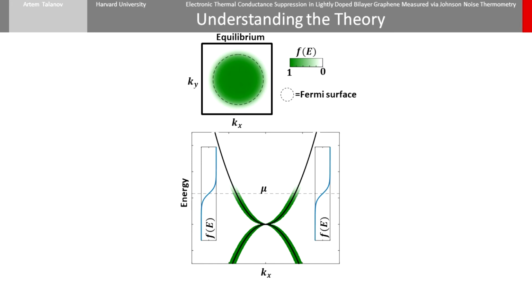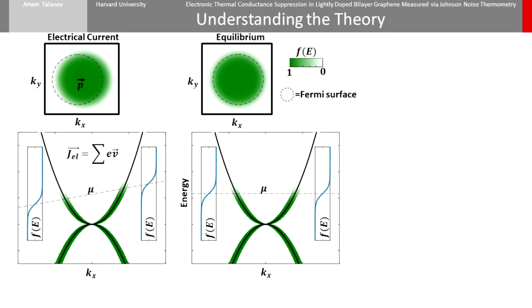I will now try to explain in an intuitive way why electron-electron scattering as the dominant source of collisions can cause such a strong suppression of the Lorentz ratio. Here I am plotting an equilibrium Fermi distribution of a parabolic band at non-zero temperature. The top plot shows occupied states in kx-ky space, and the bottom plot shows an energy momentum cut. I'm also plotting the Fermi function for the left and right sides. Now, to create an electrical current, I can add a uniform momentum shift like this to the entire Fermi sea. The effective chemical potential for right movers is higher than for left movers.